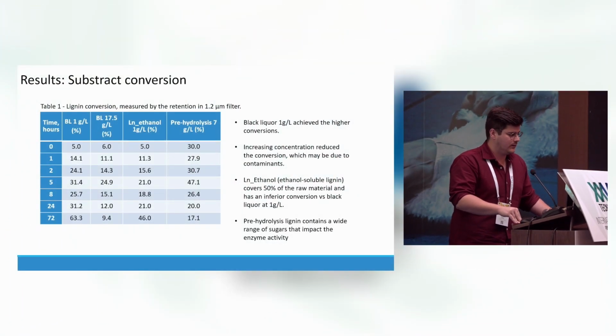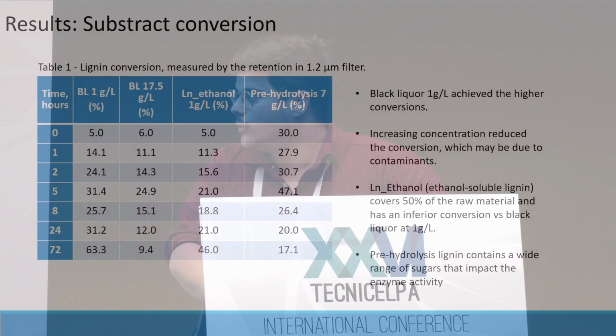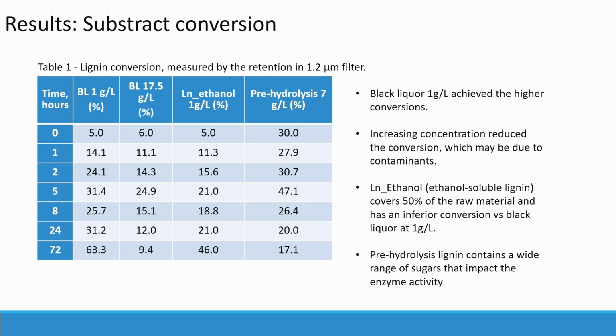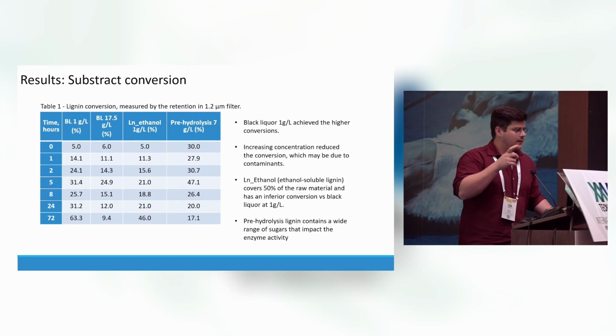The molecular weight is inferior, and in theory it should be more reactive, but due to sugar contaminants, we didn't see those results. One more point about this table is the comparison between the direct treatment of black liquor at 1 gram per liter and the fraction that is soluble in ethanol. In theory, we think that the ethanol soluble lignin is more purified, a cleaner lignin. However, the reactivity with the enzyme is inferior.